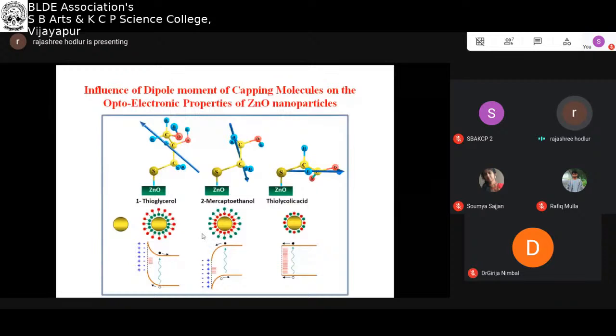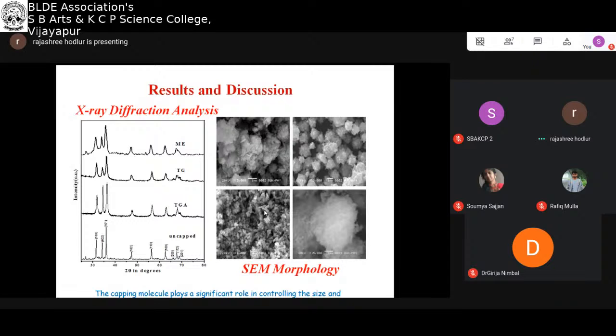In this work, our focus was to synthesize zinc oxide nanoparticles using thiols as the capping agent, and we studied how the dipole moment of these capping molecules changed the optoelectronic properties of zinc oxide nanomaterials. As an example, here you can see we analyzed using X-ray diffraction. We adopted the aqueous route for synthesizing these zinc oxide nanoparticles, and various capping molecules were used to control the size of the particles, like thioglycolic acid, thioglycerol and mercaptoethanol.